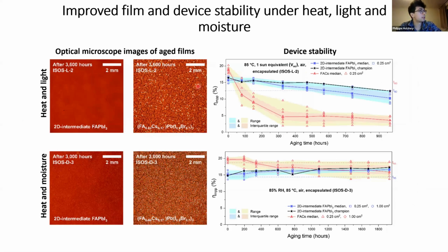And so we measured the stability for the device as well. On the left is a bit more film stability. So those are optical microscope images. So this is of the 2D to 3D FAPbI3 film after 3,600 hours encapsulated in light at 85 degrees. And that's the FA cesium film. And here you see the grain boundaries more clearly. And those white dots are lead iodide pinholes. So they're thinner, but also lead iodide.